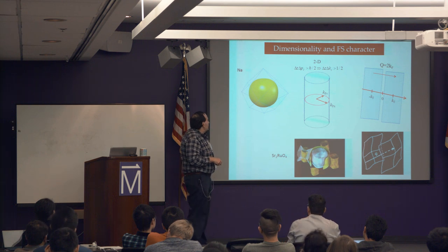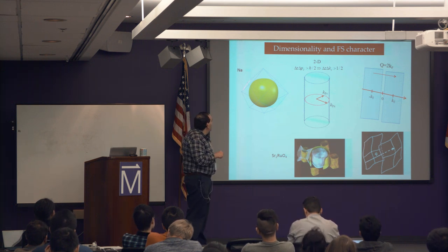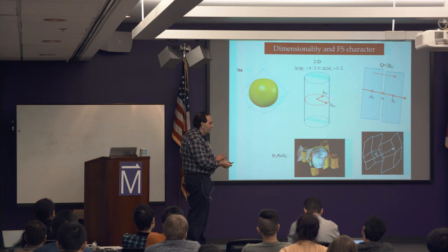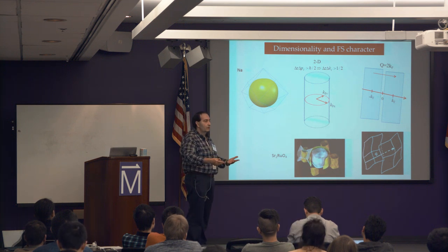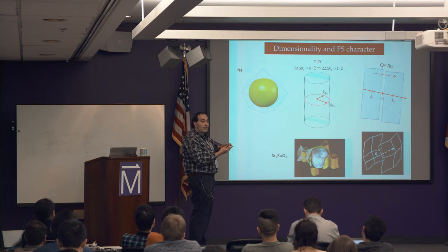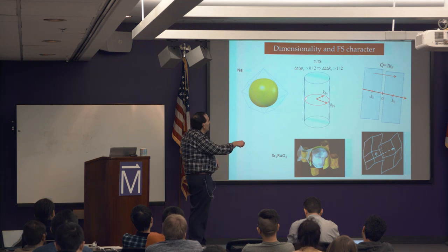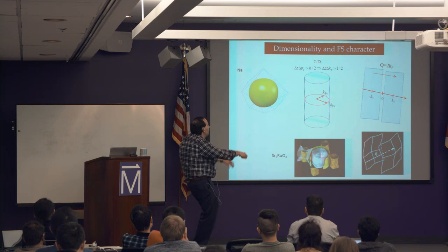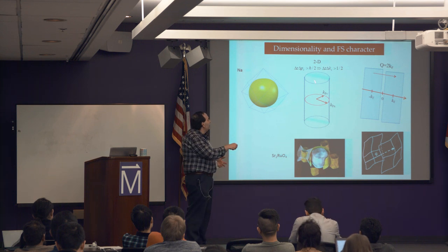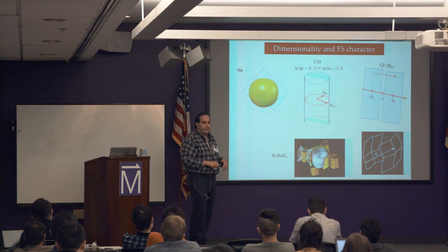No, that's okay. So the simplest Fermi surface, of sodium, is spherical. A 2D Fermi surface is like a cylinder. What does it mean? Does anybody understand what a 2D Fermi surface means? Basically, carriers are well localized in a plane. So the uncertainty principle means you have a lot of uncertainty in the momentum in the direction perpendicular to the planes. In the plane you have kF, and that draws a circular Fermi surface. Because of the uncertainty, this gives you a cylinder. So layered materials tend to give you cylindrical Fermi surfaces. And if you have a tight binding, some coupling between the planes, this will induce corrugations on the Fermi surface.